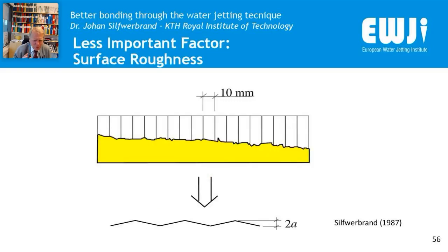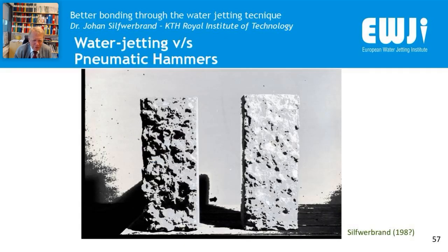Roughness, that is a less important factor. I have read so many reports by researchers in the area of concrete repair, and they all think that roughness is the number one factor influencing the bond. But unfortunately, they all come to the same conclusion, that it has a minor importance. And I can show you why from my old tests. This is just to show you water jetting versus pneumatic hammers. The roughness is twice as large for water jetting as for pneumatic hammers, but that is not the reason why the water-jetted surface is superior.